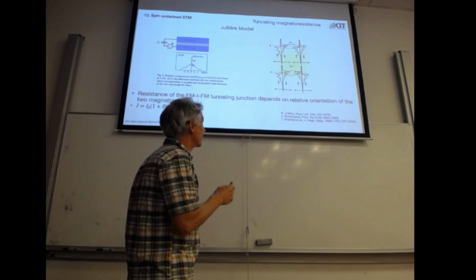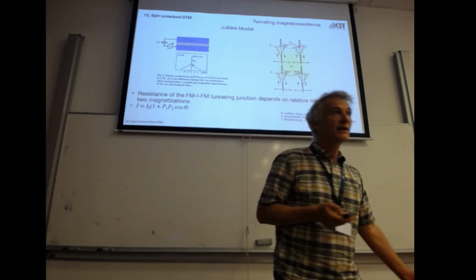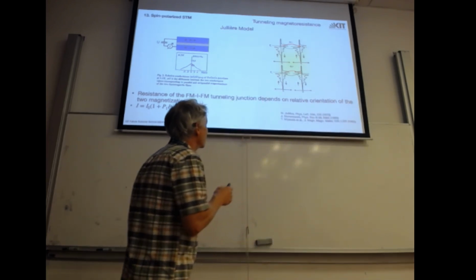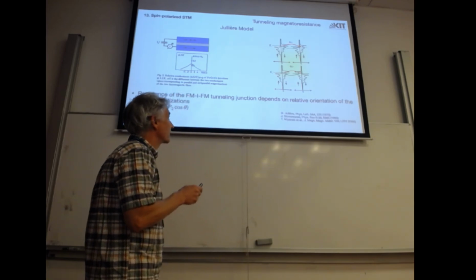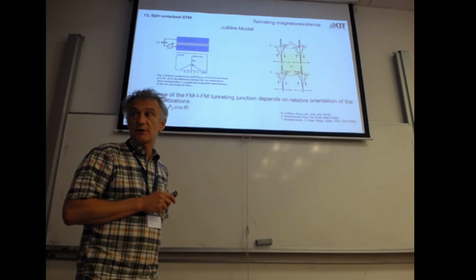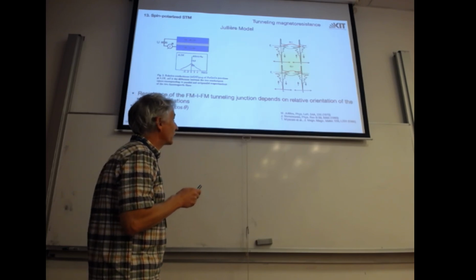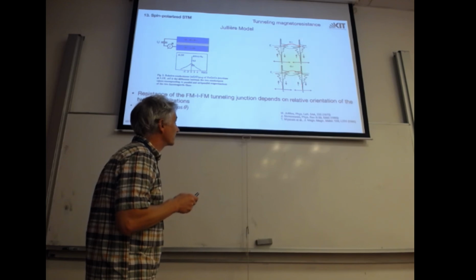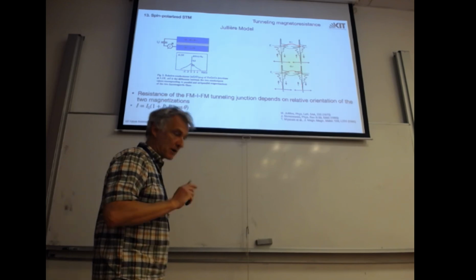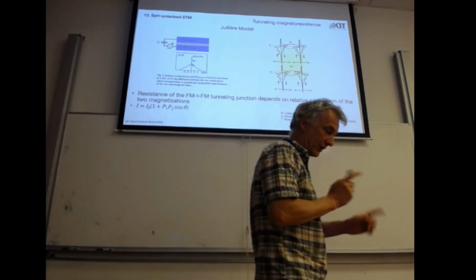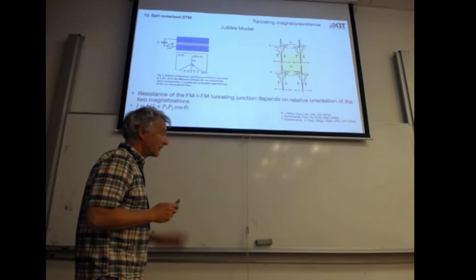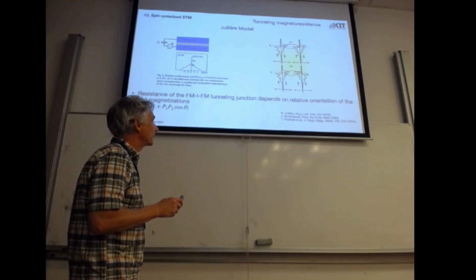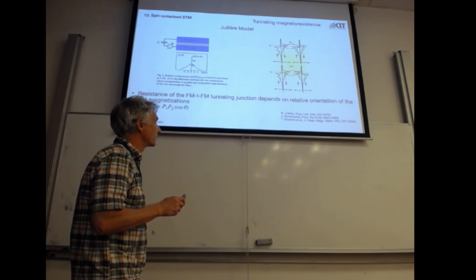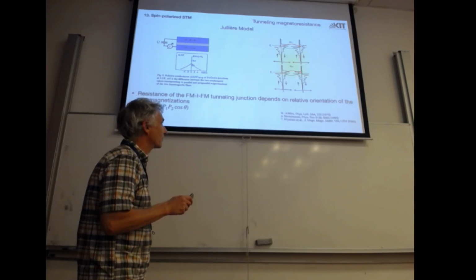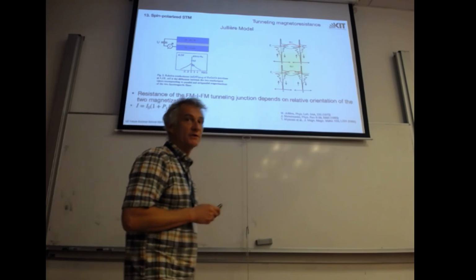And you remember that these currents are proportional to the density of states of both electrodes. And then you get two-component conductivity in the up channel and the down channel. Just something like this. But if you now reverse the magnetization of one of the electrodes, majority and minority spin character exchange, essentially. But the electron spin is conserved, so I go from these minority states to these majority states, and from these majority states to minority. So it's like G up down plus G down up.